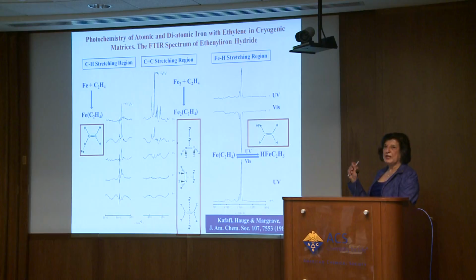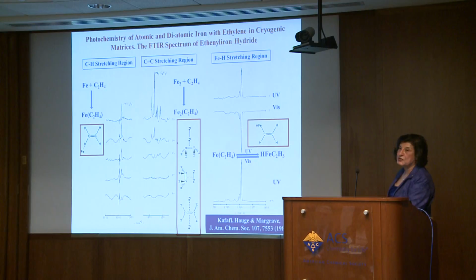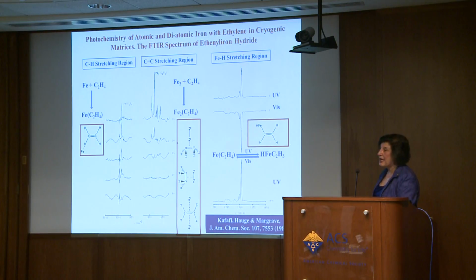When we irradiated the matrix with ultraviolet light, we noticed that this product disappeared, and we noticed a peak in the iron hydrogen stretching region, signaling again the activation, in this case, of the CH bond. So iron atom inserted into the CH bond to form this vinyl iron hydride. This reaction was photoreversible: if you shine visible light on the matrix, you get back the iron hydrogen bonded complex. You can see it going down with the visible light and going up again with the UV light.